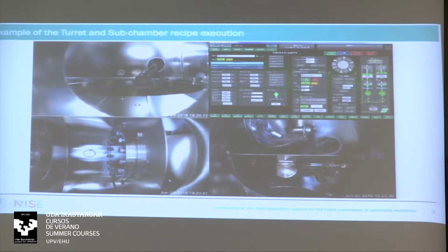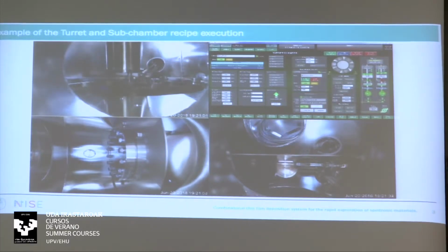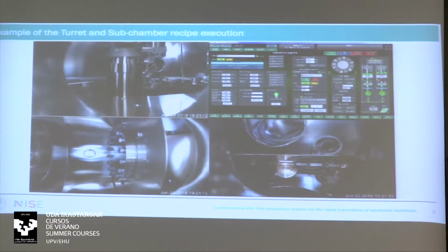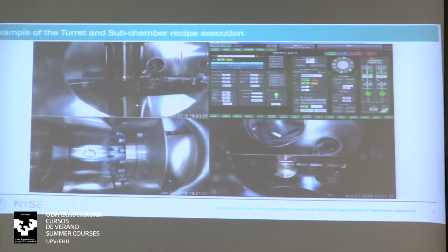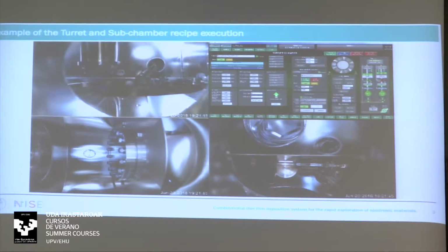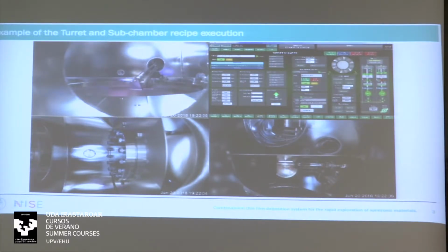That's a quartz crystal that's monitoring the rate. You can see a flash of the magnetrons because it takes a few seconds to deposit a single layer. Now there's the real substrate holder. It's rotated, heated, goes down into the deposition. That's the plasma lighting. You can't see it actually. And then the film has been deposited. It takes 2 seconds per angstrom approximately. And then now it's moved over here, and we're going to do some other things. There we are. That's basically how it works.